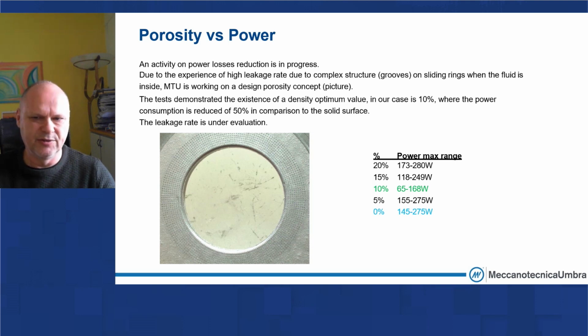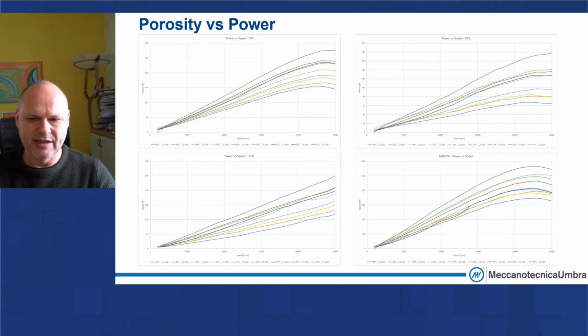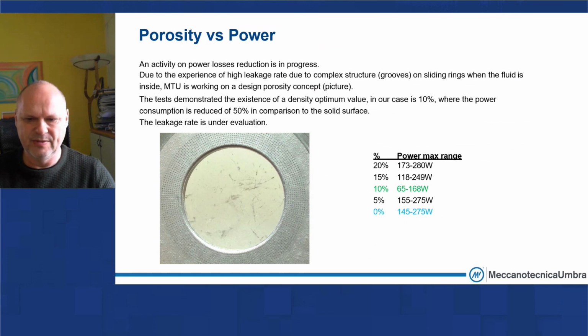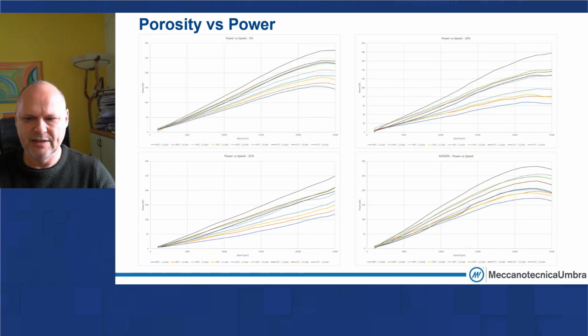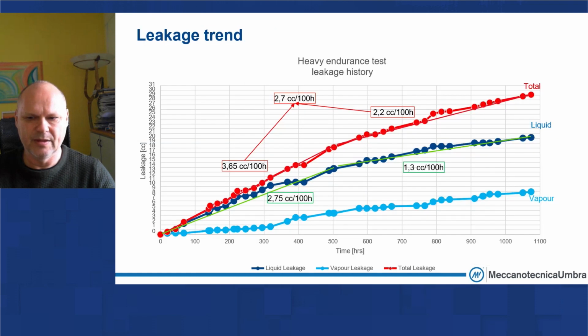Of course, this is not for free, because at this reduction of power consumption, the leakage rate increased. These are the curves, but we can summarize the result in this picture. So we have in 1,100 hours, so 4 times lower than the other test, an amount of leakage very similar to the other test. So this means that we have around 4 times the leakage with this kind of solution.